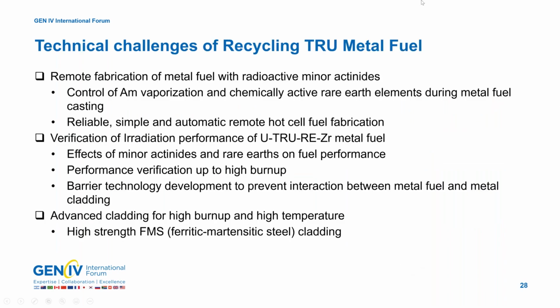You may know that this TRU fuel has highly radioactive elements like curium and americium. Because of that, this fuel should be handled in a shielded environment like hot cells. So the fuel needs to be fabricated in the hot cell remotely. So that is a challenge for the fuel fabrication. Also, americium is volatile. So during the melting of the pin ingot at high temperature, americium can be evaporated. So that evaporation needs to be controlled.